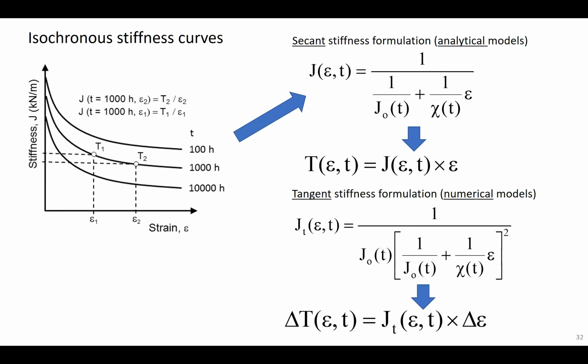And in order to model this material in a FLAC code, we had to take the secant stiffness formulation, which we've seen before. You can see the left-hand side here is the stiffness curves. Here is this secant stiffness formulation that I was explaining. But in a numerical model, you don't want the secant stiffness. What you want is the tangent stiffness formulation, because these models are solved for incremental strains. And so you have to differentiate this formulation that you see here and turn it to a tangent stiffness formulation that you can then embed in your numerical code.